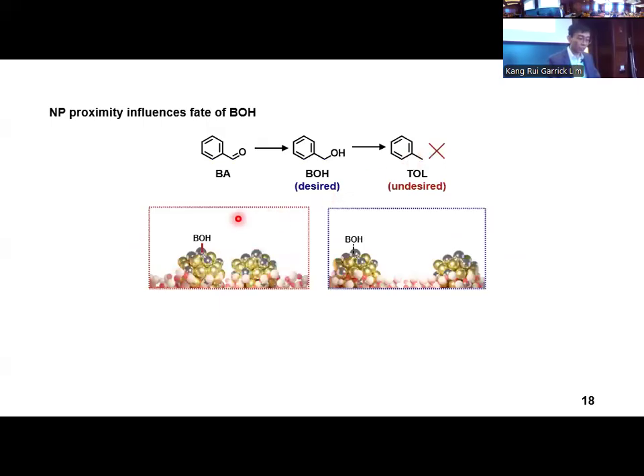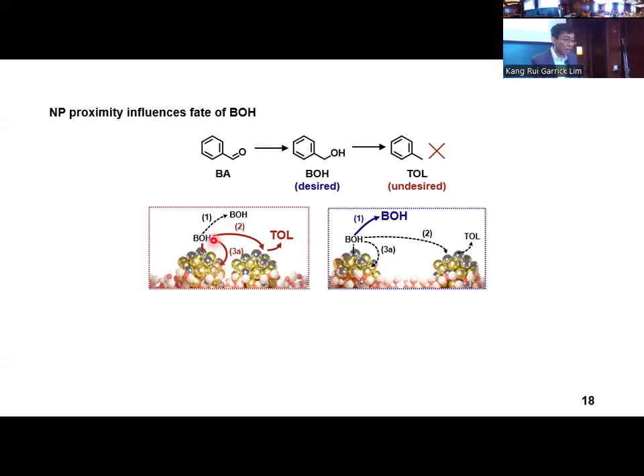Here, we argue that the as-produced benzyl alcohol adsorbed on the nanoparticle can either, 1. dissolve into the bulk as free benzyl alcohol, or stay within the nanoparticle's vicinity. For the latter scenario, benzyl alcohol can dissolve from the nanoparticle and be readily reabsorbed by an adjacent nanoparticle or back to the same nanoparticle without diffusing into the bulk. In both cases, paths 2 and 3 yield toluene and depend on the interparticle distance, as a higher local benzyl alcohol concentration would increase effective benzyl alcohol reabsorption to form toluene.